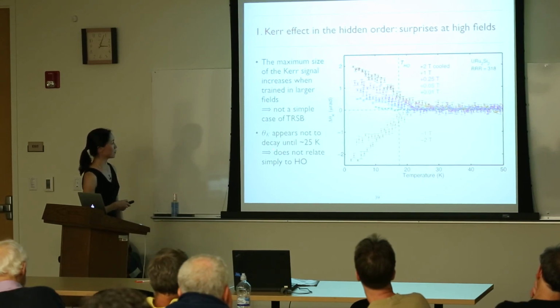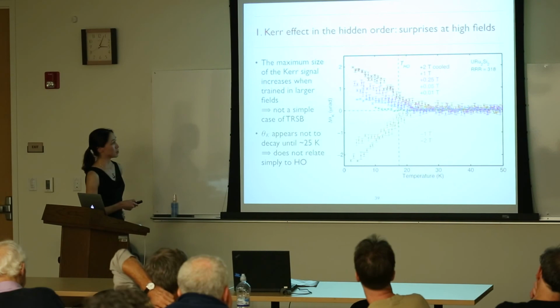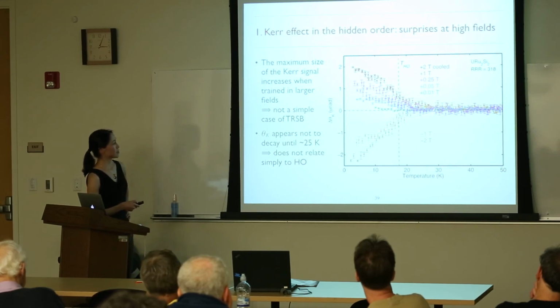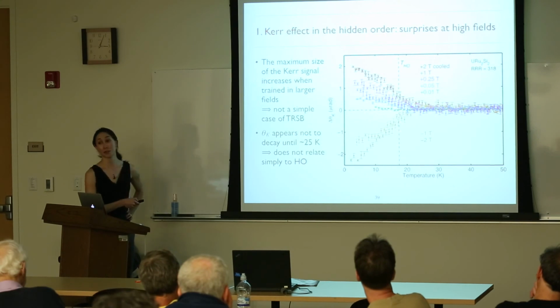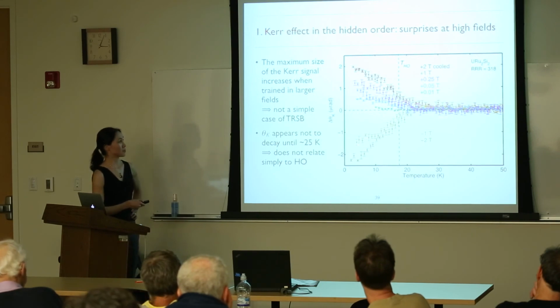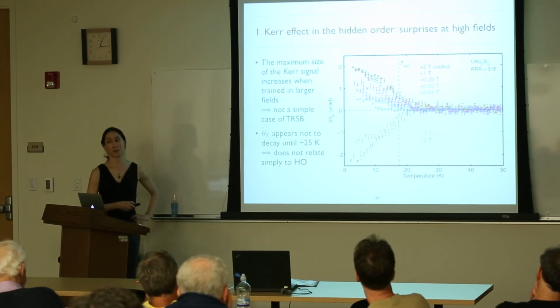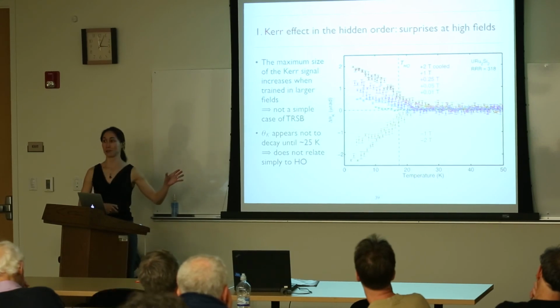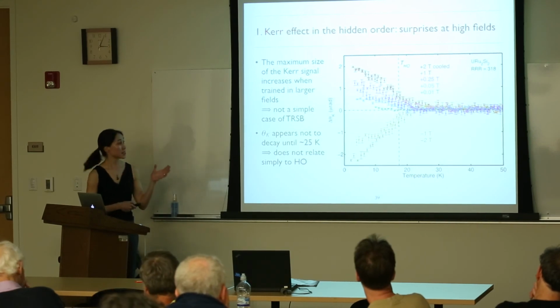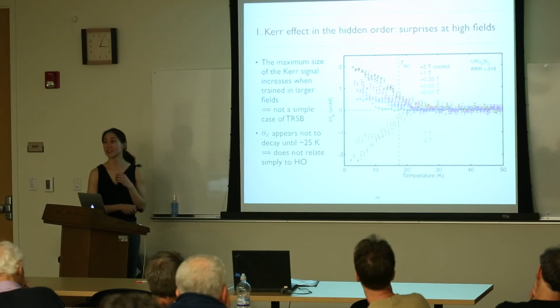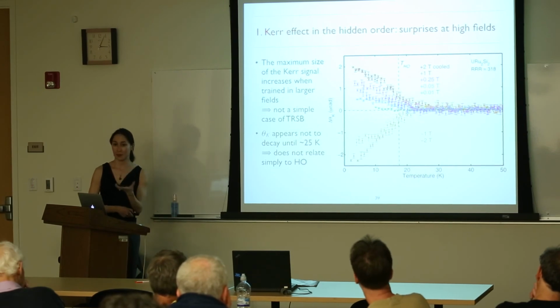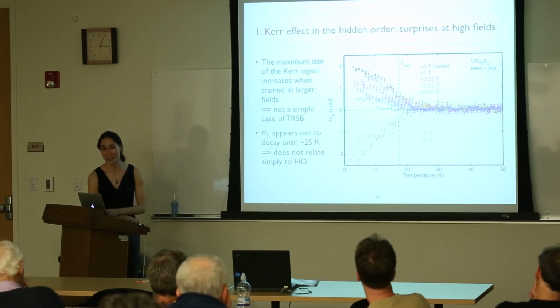The second thing that I like to point out is, again, it becomes clear when you look at this high field data that the Kerr angle doesn't decay to 0 until well above the hidden order temperature, so around maybe 25 Kelvin or so. So we're not able to very simply relate what we see here to the hidden order. We're not sure that what we're looking at has anything to do with hidden order at all, in fact. Nevertheless, other people have seen some interesting things starting at 25 Kelvin, so there's certainly a lot more work to be done there.